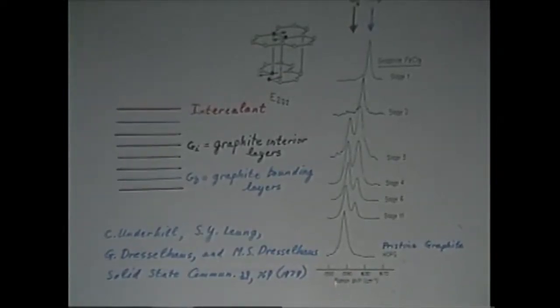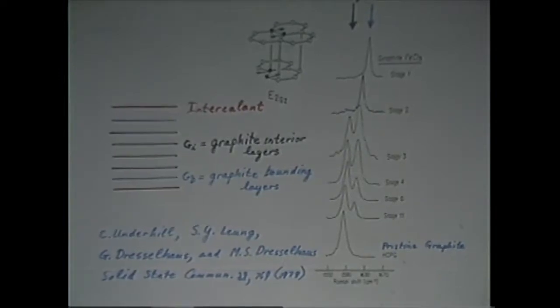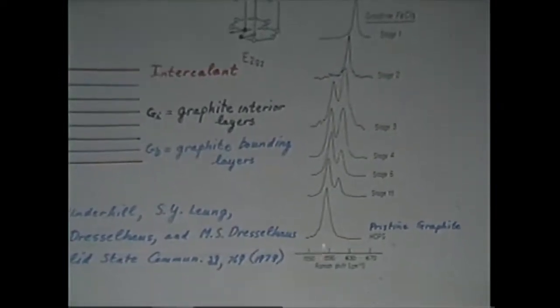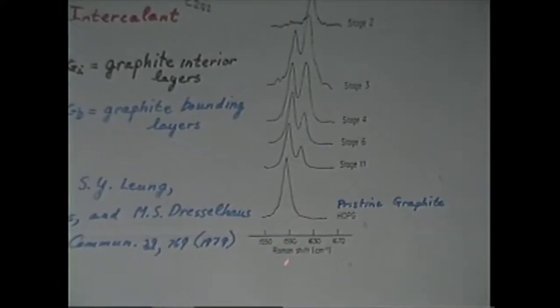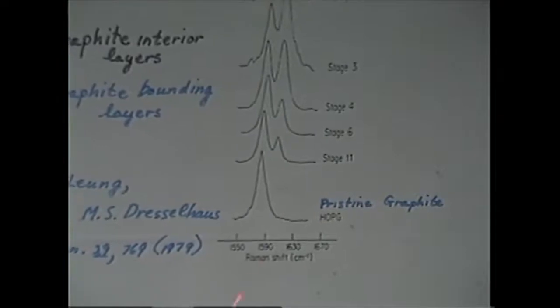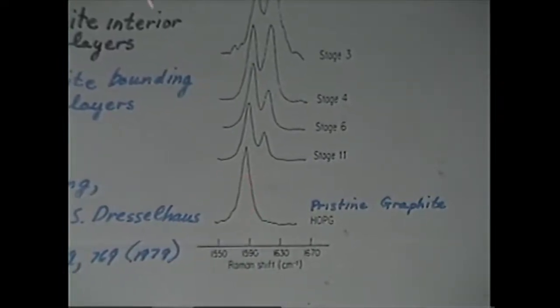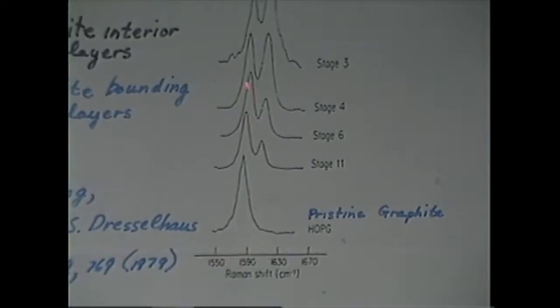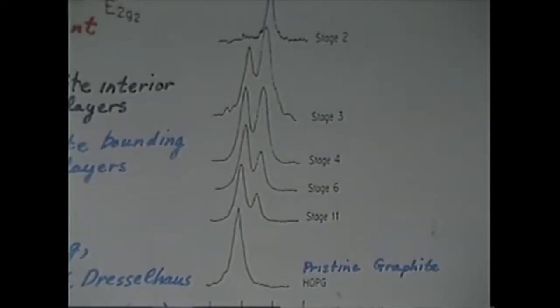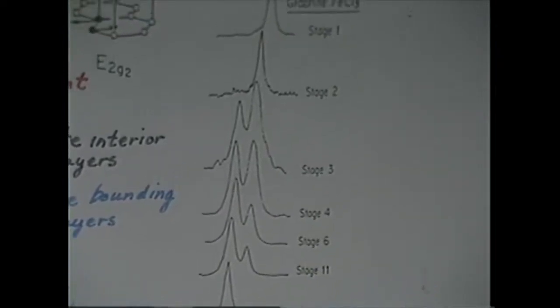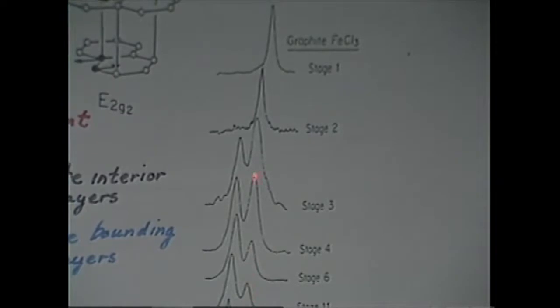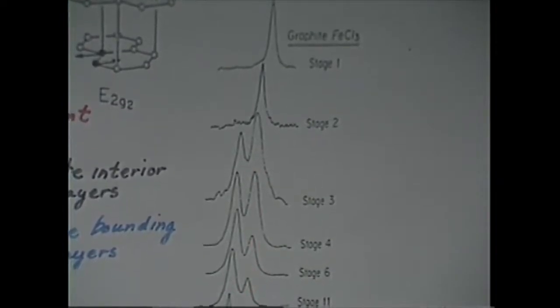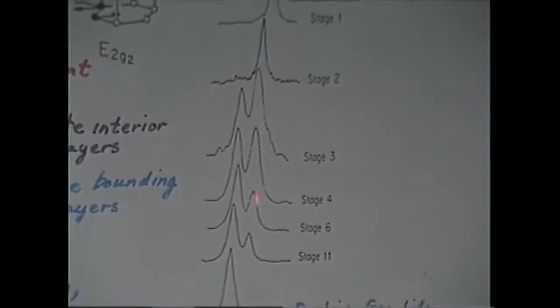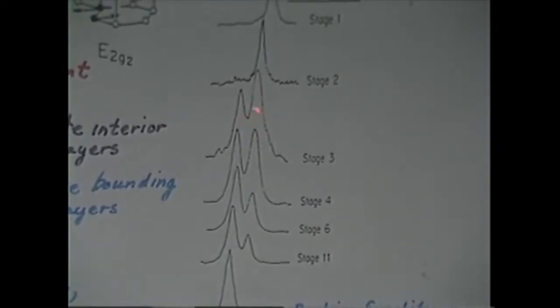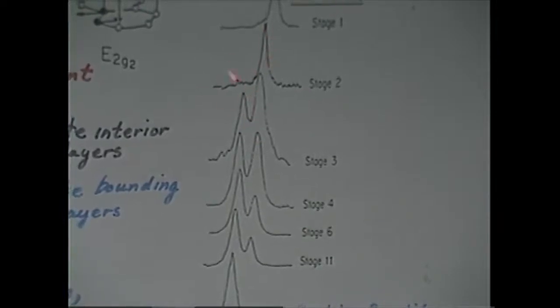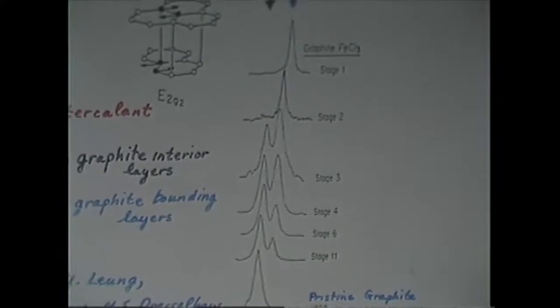Well, here again, we got results that were kind of slightly unbelievable. The effect of intercalation on the graphitic modes was very, very small. Here we're at about 1,600 wave numbers. Here's the graphite line, the E2G2 mode, and it hardly changed as we added intercalant and went up in stage. However, there was some evidence that intercalation did something, in that we had a second Raman line that was upshifted by about 20 wave numbers, and this line increased in intensity as the stage index decreased, that is, as the concentration increased, and finally at stage 2, this first line disappeared, and also for stage 1.